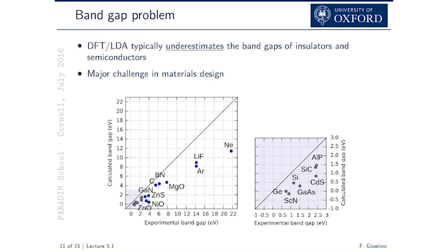So the point is that one could do that, but let's make an example. For the perovskite I was discussing yesterday for the phonons, the DFT gap is 0.5 eV. If you multiply that by 1.4, so if you increase it by 40%, using kind of an empirical rule, that will give you 0.7 eV. The experiment is 1.7, so you're off by 1 eV, okay?